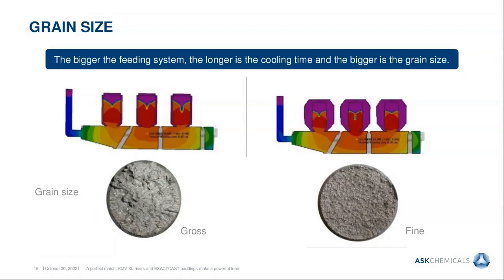As we were mentioning, by reducing the volumes of the feeding systems and going from traditional feeding solutions to the KMV XL with less volume, we also have the possibility to reduce the neck sections of the feeder and the casting. These particular areas have a lot of differences when using a traditional feeder solution compared to the KMV XL riser. For example, when using the traditional systems, we have wider necks, and in those areas we will have longer solidification times. This will result in a grain size quite different from the grain size that we would have when using the KMV XL risers with the smaller necks.